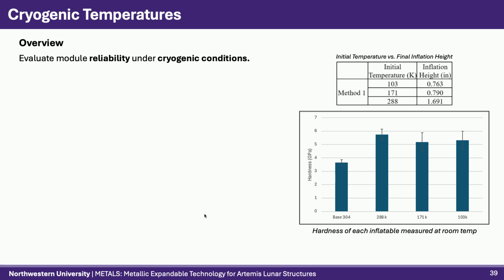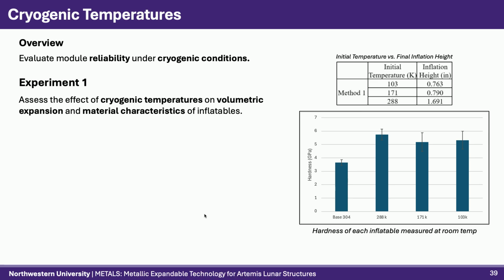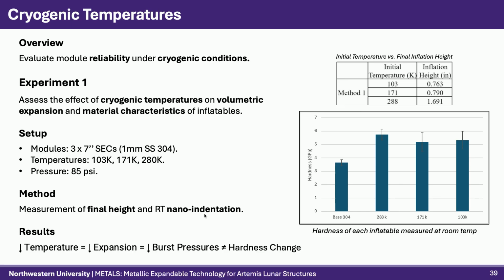We conducted 2 experiments with identical inflatables to test if they are reliable under cryogenic conditions and to determine the ideal inflation temperature. For our first experiment, 3 inflatables were inflated at different temperatures to identical pressures before each was nano-indented at room temperature to determine post-inflation yield strength. The inflation heights were then measured as a proxy for comparing the changes in volume. Our results showed that inflation heights and burst pressure decreased with temperature, but material hardness did not change.